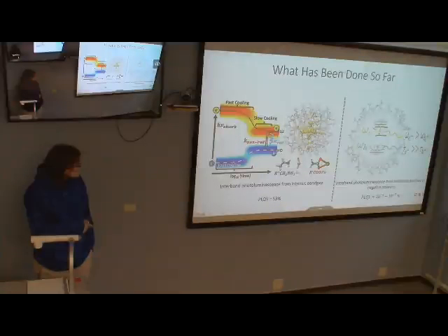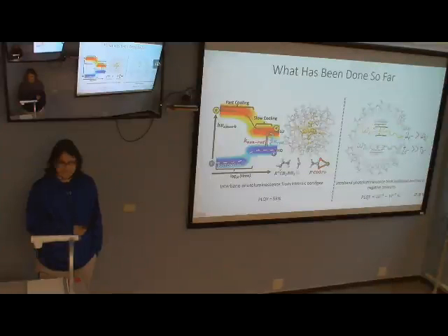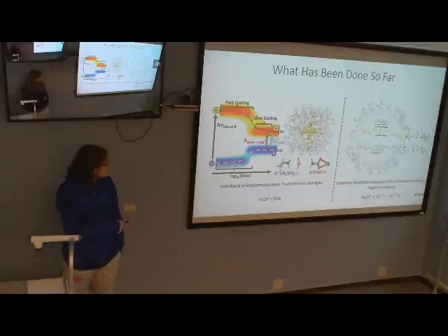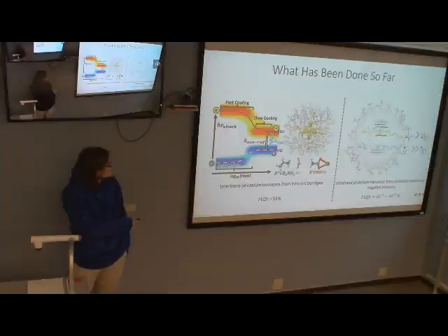On the left, we described the excited state carrier cooling and luminescence properties of a small perovskite nanocrystal atomistic model. So that's what this is here. It's a 2 by 2 by 2 unit cell, passivated with ligands, which would reflect the kind of environment it would be in a colloidal system, approximately.